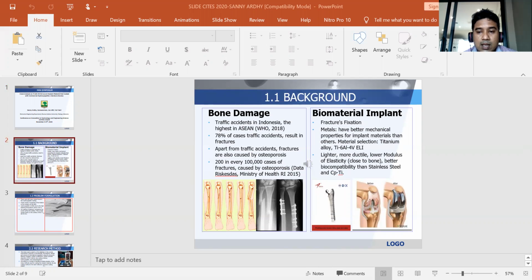This condition can result in the implant material loosening, which can lead to failure in the growth of new bone tissue around the implant material that is placed in the body. In the sense of the word, the process of fusing implant with the bone doesn't occur. The coating used is derived from bovine bone and commercial hydroxyapatite in micro and nano sizes using dip coating.